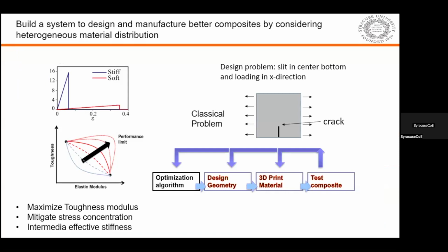Okay, so with those two bases, we want to study the architecture, and we also want to find the binding material between those blocks that is much more flexible and will fail at much larger strain, ideally hyperelastic. Then we can mimic nacre and combine the stiff, rigid phase and the flexible phase. We aim to obtain a material with an intermediate elastic modulus but much higher toughness.